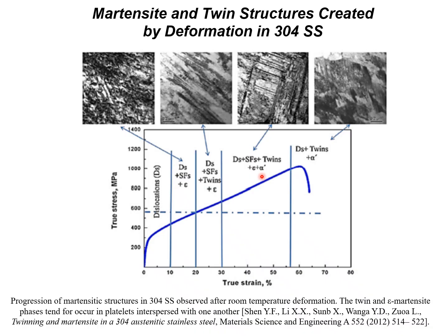Now, in this case, they've identified something called alpha prime, and it was not clear what they mean by alpha prime, because alpha typically means a ferrite, and alpha prime is not necessarily a quenched martensite where you've quenched in carbon. So I'm not quite sure what's going on here, although it is conceivable to go from the epsilon martensite, which is the hexagonal phase, to a body centered cubic phase by shearing. So basically,